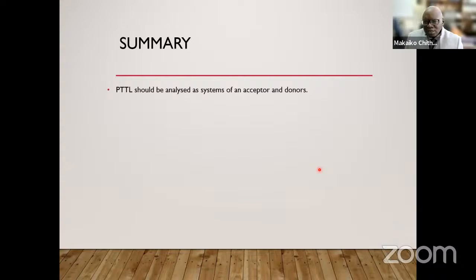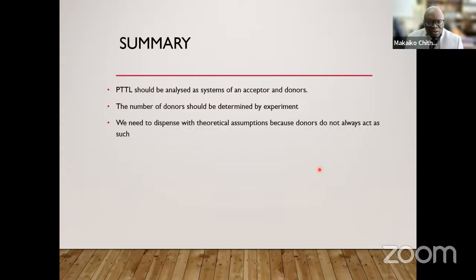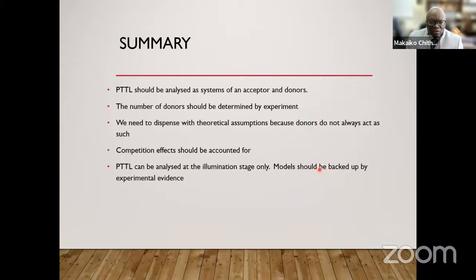Okay, so to summarize then, photo transfer should be analyzed as a system of acceptors and donors. Okay, it shouldn't be based on guesswork. The number of donors should be determined by experiment, and theoretical assumptions are a problem, and in my opinion, we need to dispense with them because donors don't always act as such. And also when you have competition effects, you need to account for them.